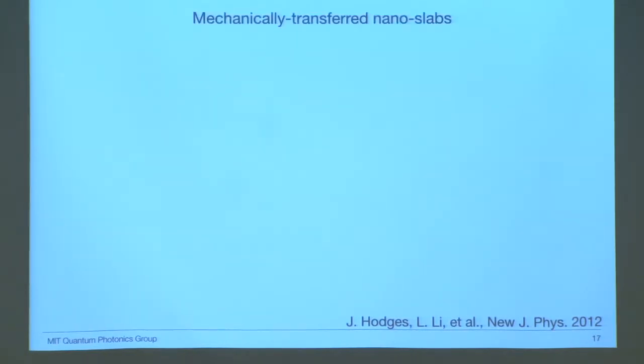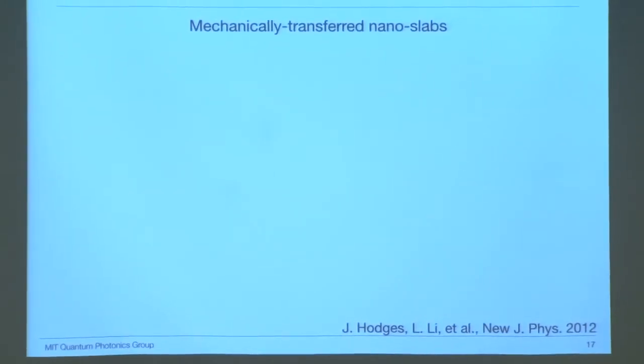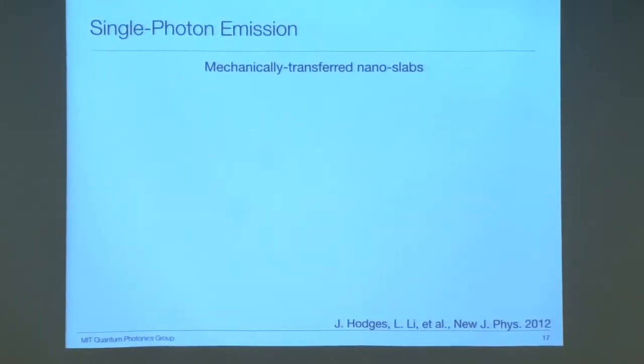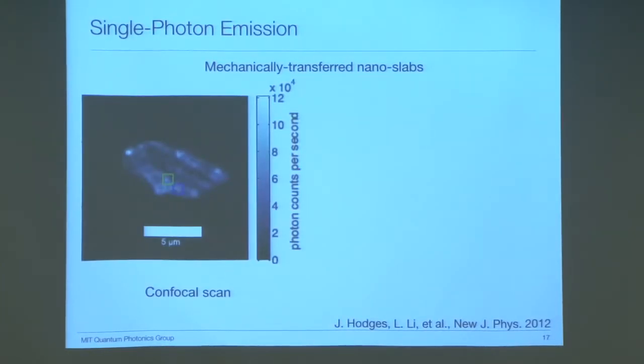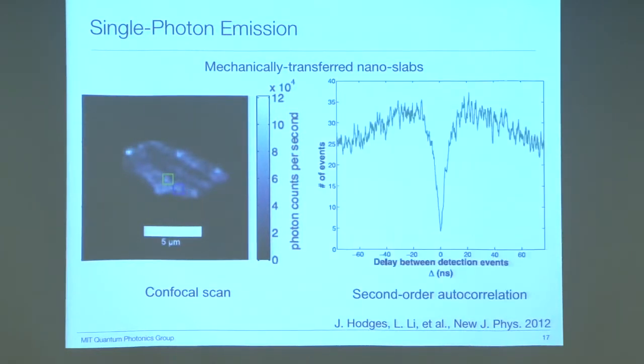We also checked the optical property after these diamond nanoslabs are transferred onto a cover glass. This is a confocal scan again, but for the transferred diamond nanoslabs. A g2 dip below 0.5 indicates that this NV inside of the green square is a single photon emitter. So far, we can claim that this method produces a cleaner diamond membrane, which has better optical property compared to the crystal ion sliced diamond membranes.